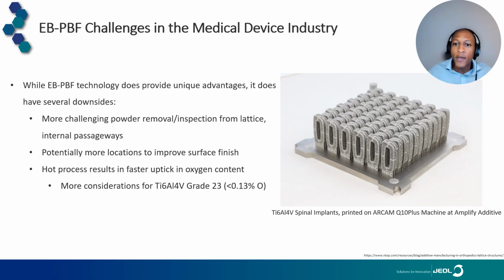Lastly, if you do have a customer that requires the use of Ti-64 grade 23 or ELI powder, which is more commonly known to be used in the medical device industry, the electron beam powder bed fusion process does have a faster uptake in oxygen content due to it being at a higher temperature. The powder particles overall for Ti-64 are susceptible to moisture absorption if you're not careful. Putting that powder into the machine and having the machine maintain that elevated process temperature can result in a slightly faster uptick in oxygen content from build to build.